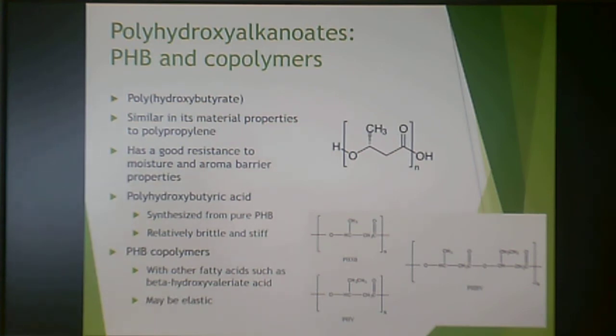This is one of the PHAs, PHB, polyhydroxybutyrate. It is very similar in its material properties to polypropylene. And again, it comes from bacterial fermentation, so it comes from a non-crude oil source. It has good resistance to moisture and aroma properties. Polyhydroxybutyric acid is synthesized as pure PHB, and this is relatively brittle and stiff. But if you create a PHB copolymer with other fatty acids like beta-hydroxyvaleric acid, you can create something that's a lot more flexible and can be up to something that's elastic. So you can tailor the properties somewhat from something that is from a bio-friendly source but has material properties similar to polypropylene.